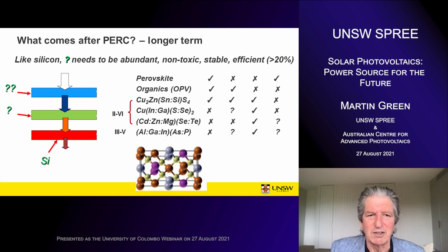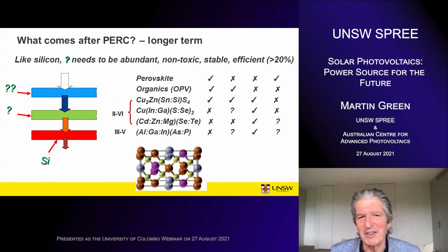So this is clearly a good way for the industry to go. The real challenge has been to find a suitable material for stacking on top of silicon. It needs to have a higher band gap than silicon, and it needs to have all the desirable properties that silicon possesses, which is abundant. Silicon is the second most abundant element in the Earth's crust. It's non-toxic, it's stable, and it's efficient. You need an efficiency of at least 20% from these cells that you're going to stack on top of silicon. So finding materials that meet all those 4 criteria has been the problem.